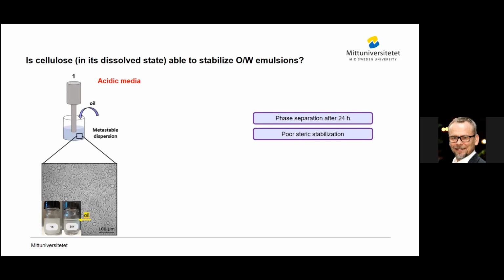And that is, of course, due to several things. One is steric stabilization. Another thing is that you don't have the affinity to the surface that hard, so you will lose oil. The oil will leach out, you could say, from the oil droplet, and you can soon have different kinds of escaping that makes a macroscopic phase separation possible, larger lumps of oil together.